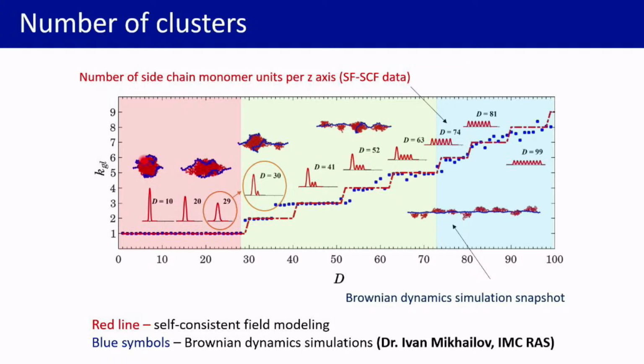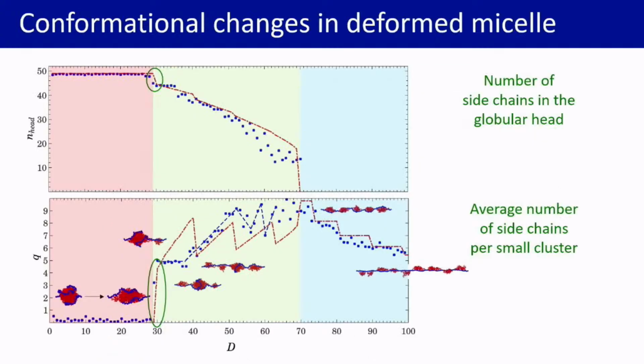So we see nice Brownian dynamics snapshots of the deformation of the micelle as a whole, appearance of the first cluster, the following cluster, and disappearance of the big head. So in full accordance with our self-consistent field result. So these plots illustrate conformational changes in deformed micelles, namely the number of side chains in a big head and the number of side chains in one small cluster.